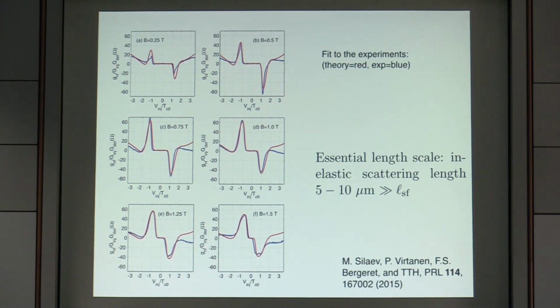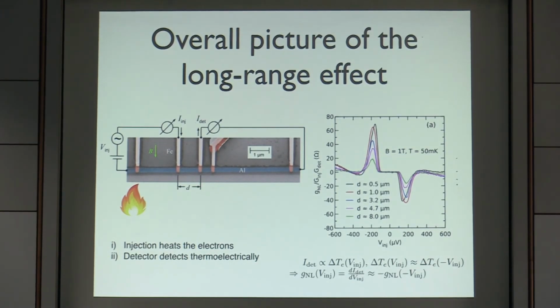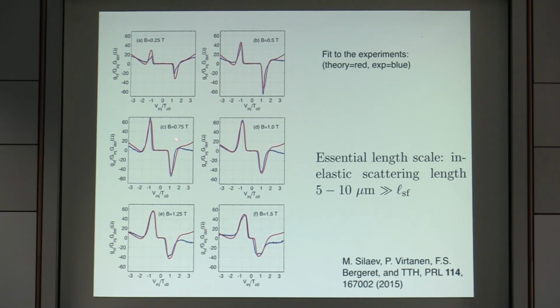Yes, because basically to see this thermoelectric effect, you have to have this finite spin polarization of the injector, of the detector. There is still another experiment by Beckmann where they showed that, of course, if you look at the exact symmetry of these curves, the red curves are theory curves, and the blue curves are the experimental curves. You can see that these curves are mostly antisymmetric, but there is some symmetric component which actually relates to the real spin signal still in those setups. But mostly they are antisymmetric, and this symmetry of the signal tells you whether it's related with heat or spin injection.